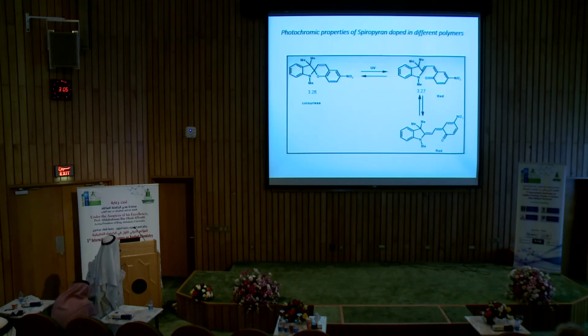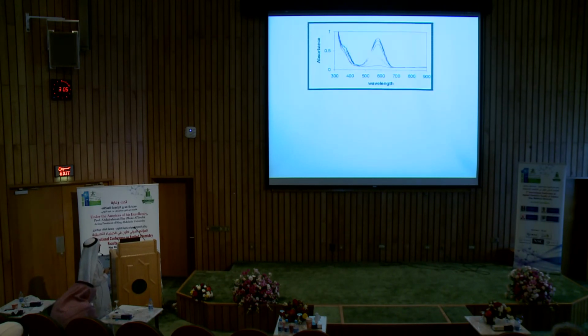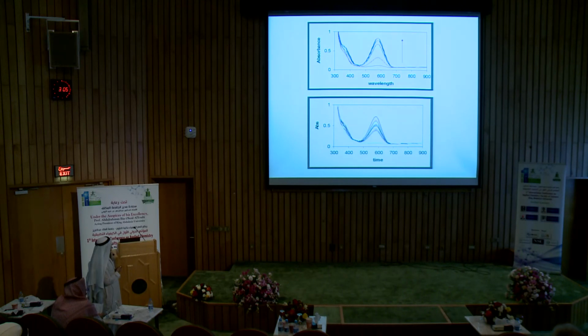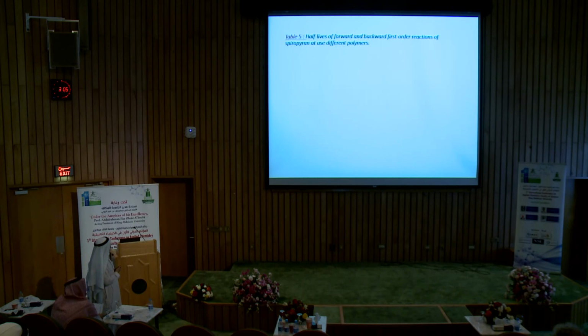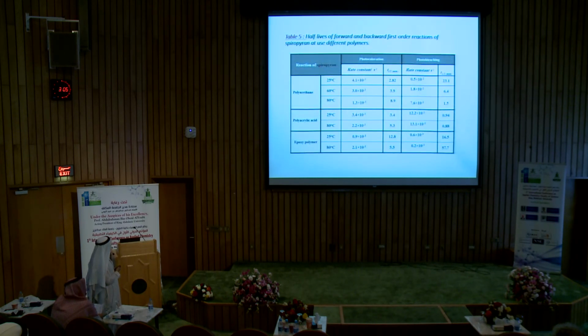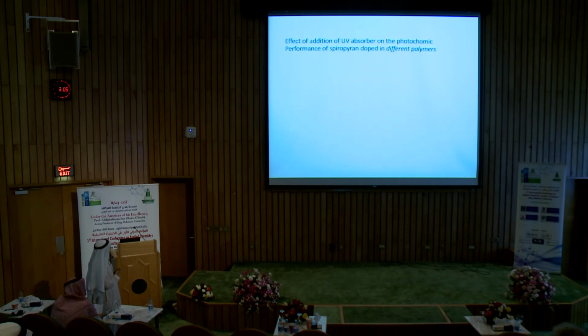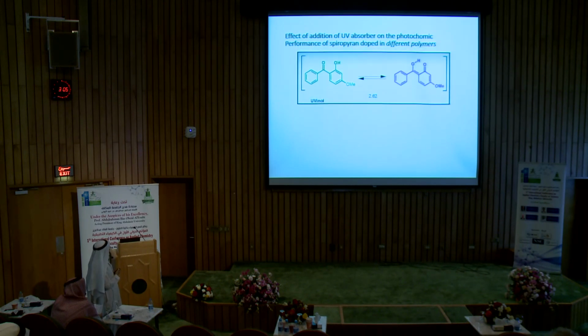This is the spiropyran compound. Spiropyran compounds absorb at something like 550, especially this compound, when irradiated with UV light. And this is the bleaching of this compound. These are the tables for the photophysical properties and rate constants. And also we studied the effect of the UV absorber on this reaction.